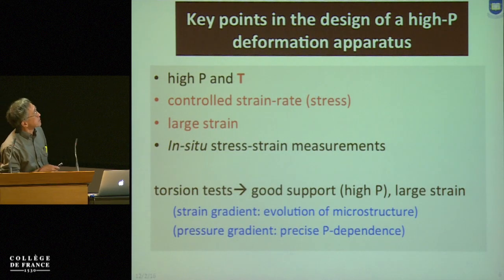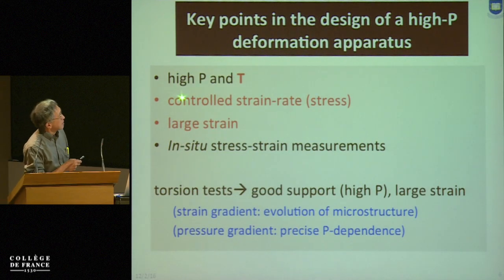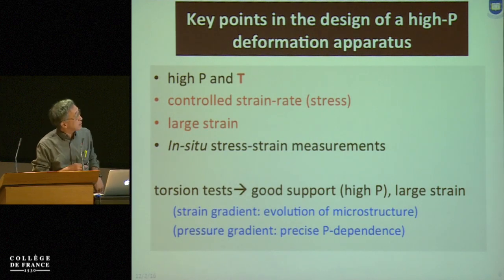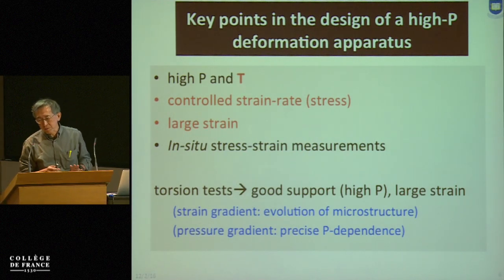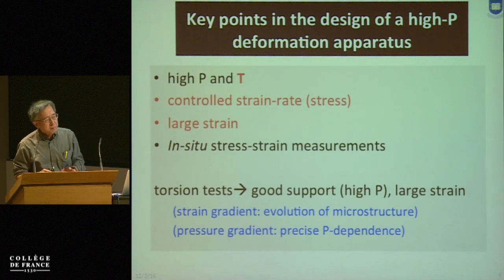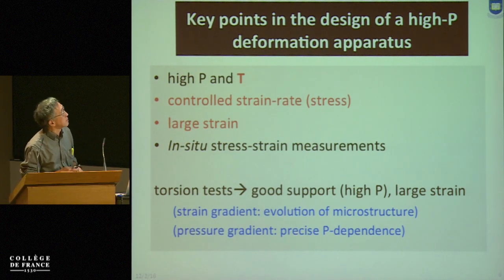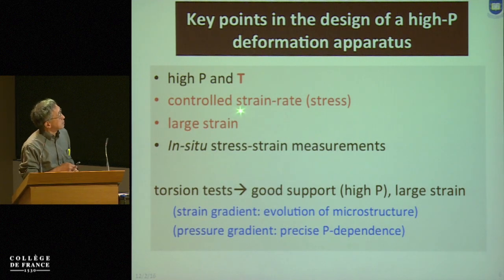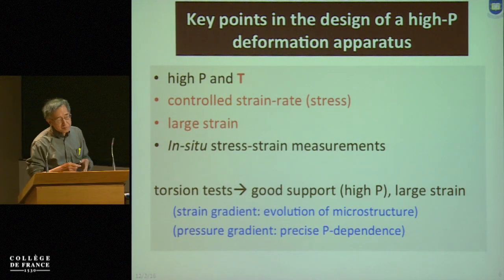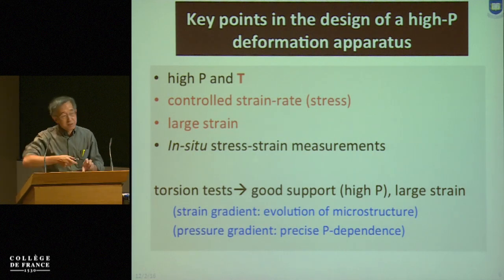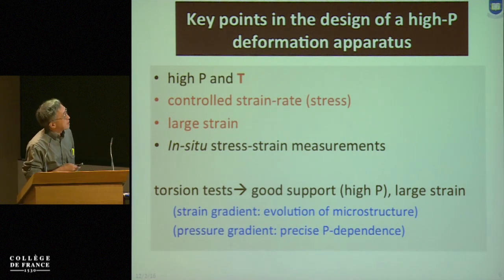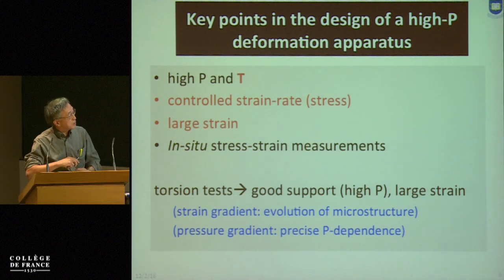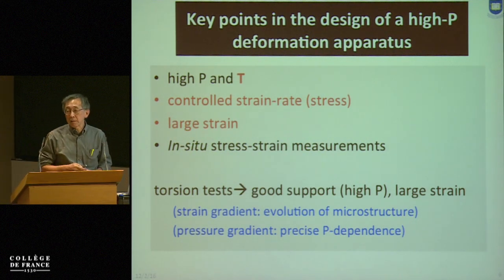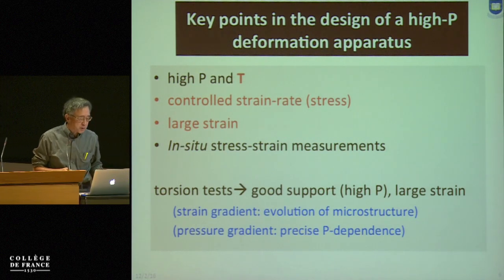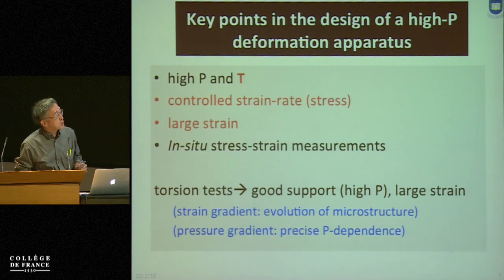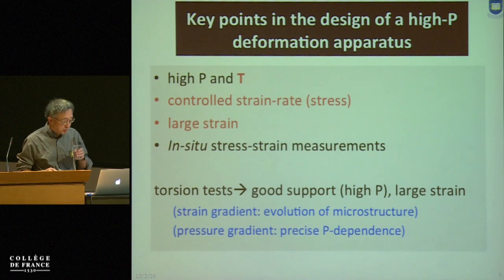So the key points in the design of high pressure experiments: you must go to high pressure, that's easy, but you must also go to high temperatures because temperature matters. Low temperature and high temperature deformation mechanisms are completely different. Also, you must have a controlled way of generating strain rate or stress by motor. And it would be nice to have a large strain, and that's why I chose the torsion design. Another important part is how you measure the stress and strain. Those are in situ measurements using X-ray. I'm going to show you in a few minutes.